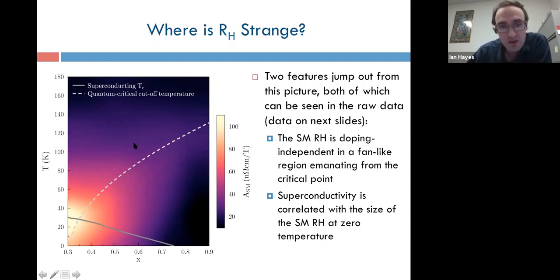The second thing I want to draw your attention to is what happens at low temperatures. So when you cross that fan-like region, the strange metal field dependence weakens, and it continues to weaken, but it doesn't weaken all the way to zero at zero temperature. There's an extended range over which you still see a decreasing RH with increasing field, and it's strongest near optimal doping, and it decreases for higher phosphorus content, and then vanishes at the same point that superconductivity vanishes. So if you go just beyond the superconducting dome at low temperatures, you see none of this decreasing RH with field, you see pure H squared. You can recover the decreasing RH with field if you go to higher temperature, but specifically the low temperature part of the Hall coefficient seems to be strongly correlated with superconductivity.